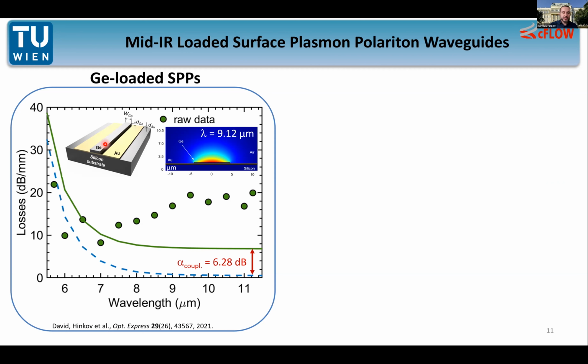The nice thing here, and we can see it basically on this plot, which shows a simulation of the cross section of the mode profile, is that by adding the germanium, while before without the germanium it extends, as we said, at 9 micron, it would extend to 90 micron or something like that, now we really confine the light and it extends just a few microns outside of the actual layer of germanium that we have. It's relatively thin here, it's 200 to 400 nanometers.